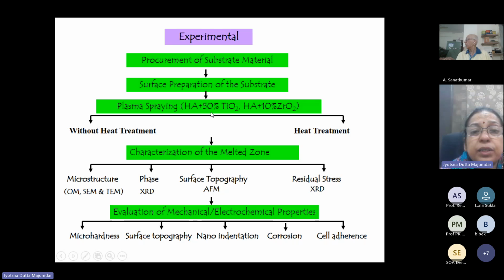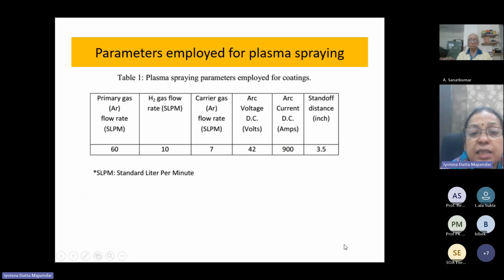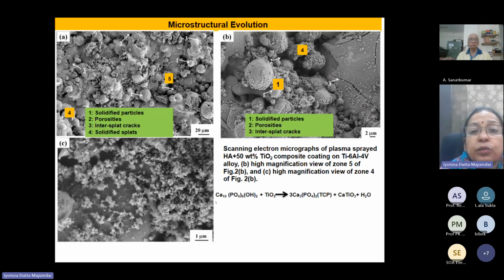So we did heat treatment so that it gets crystallized, and then we characterized the plasma spray deposited structure, and then evaluated the mechanical and electrochemical properties as well as cell adherence study. If you see the structure carefully, this is the 50% TiO2 composite coating, and high magnification views of different zones are shown here.